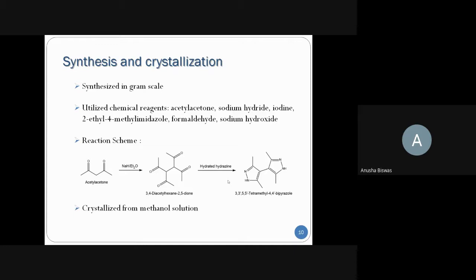Now to introduce the crystallization part, 50 mg of the compound is added to 5 ml of methanol solution in a clean conical flask, and it's heated for 10 minutes at near about 40 degrees Celsius temperature, and then it's kept for 3 to 5 days, after which transparent slender needle-shaped crystals are obtained, and these crystals are characterized by single crystal X-ray diffraction pattern.